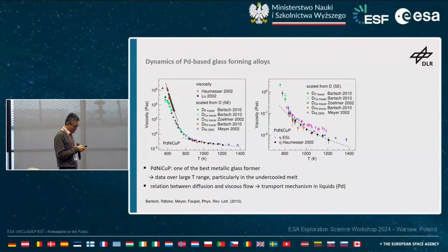The idea is to look at these noble metal-based metallic glass formers for two reasons. One is more physical. These are one of the best glass formers, so there are many data collected in this kind of composition. What is especially interesting for us is to look at the dynamic coefficients, on the one hand viscosity, and on the other hand the diffusion coefficient. This is the only alloy where the diffusion coefficient has been measured over the entire temperature range where one has a liquid. The melting point will be somewhere here, and usually we would not be able to measure this part because of crystallization, but the glass forming ability is so good that we can access even the undercooled melt.